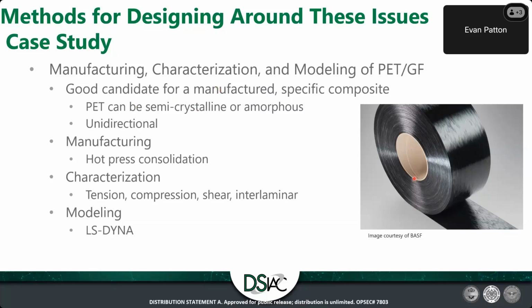And it's a unidirectional tape, and for those that are unfamiliar with composites, unidirectional means exactly what it implies. All the fibers are running in one direction, and this picture here to the right is a good representation of the material that we are using. You can see these striations in the material. These are those actual fibers, and they're all running in the tape direction. And to manufacture our test objects as well as our characterization test samples, everything was conducted using a hot press consolidation method. I'll talk a little bit more about that on the next slide.